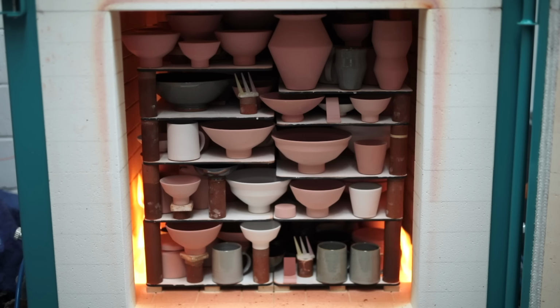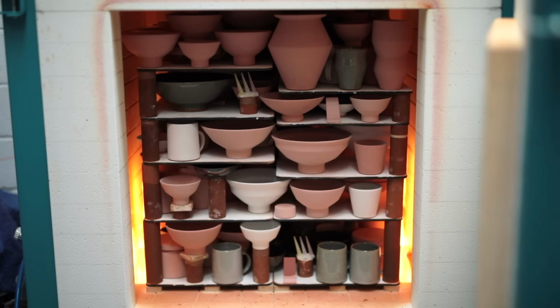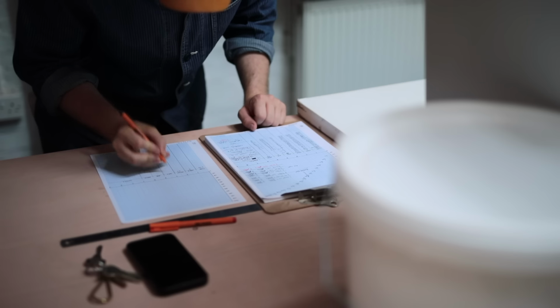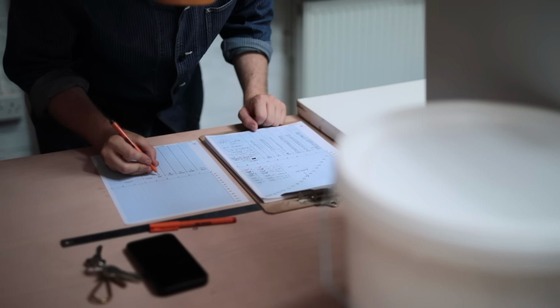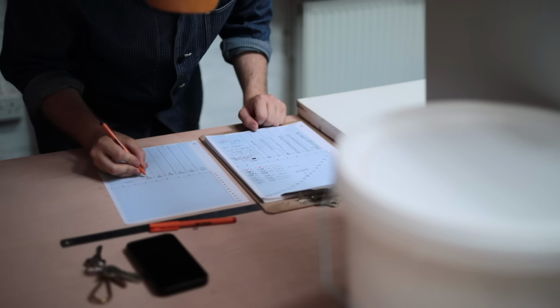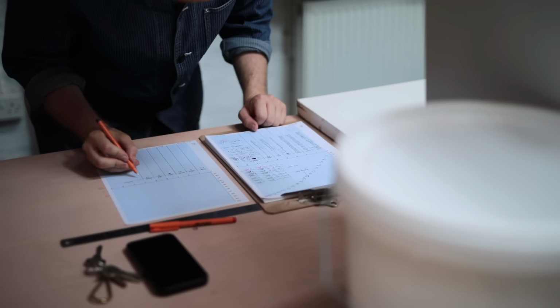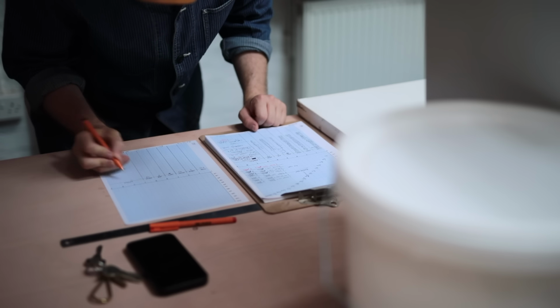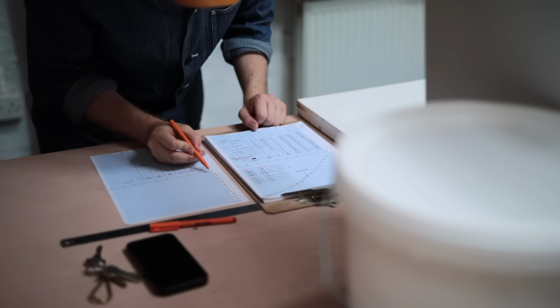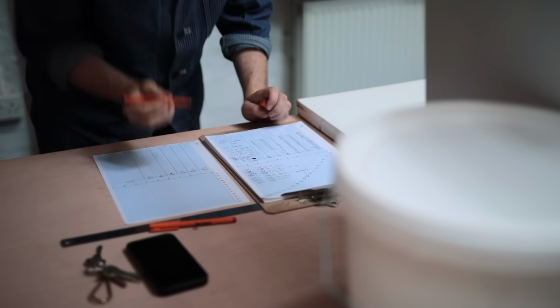The kiln is lit at 7 AM, and the firing itself takes about 9 hours from beginning to end. And for the first couple of hours, I fire the kiln up very slowly, increasing the temperature gradually, as if you rush it, pots can explode potentially. Every half hour, I log the time, temperature, the gas pressure, the air pressure, and the damper position. This way, over multiple successful firings, I can home in on firing schedules that really work for me, and it also makes it easier to repeat firings, and also see potentially where things went wrong.